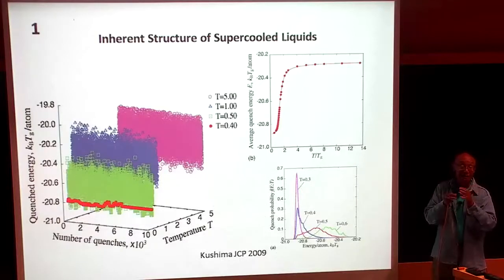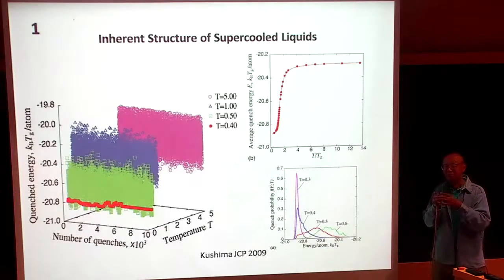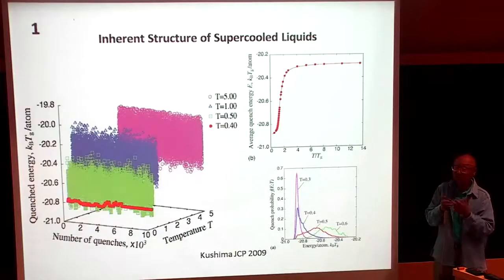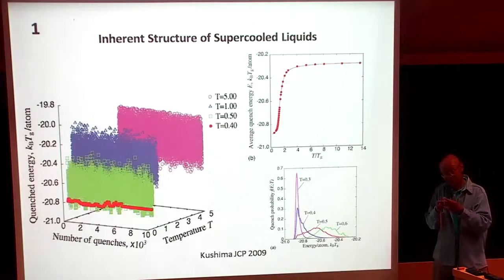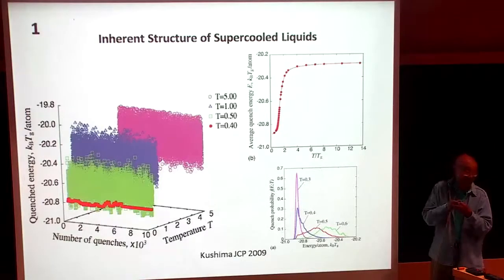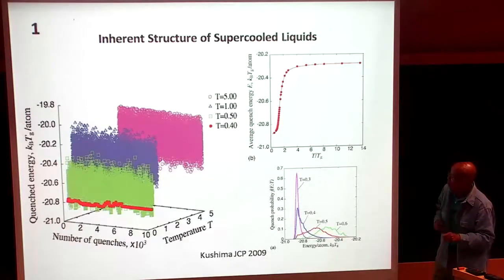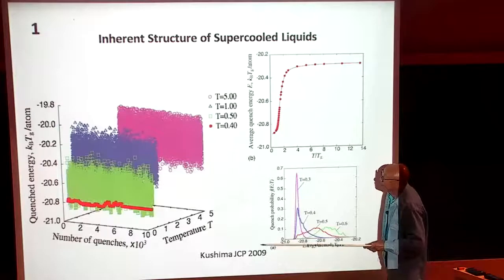Just think of that because the word polydispersity has been used. You need the two different sizes so that the system doesn't crystallize. In the early days of MD, we found out that if we use a Lennard-Jones potential with one size, it will always crystallize in FCC. We would like to keep the system from crystallizing, so you use two-size Lennard-Jones, and that makes it more difficult for the particles to find the right arrangement to crystallize. So we have a potential function, and you can run.